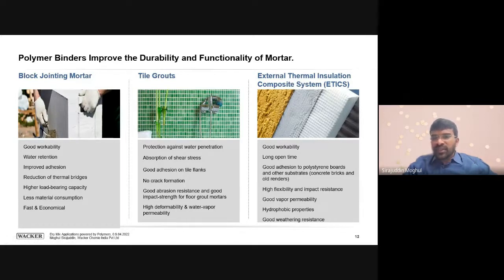It's an external thermal insulation composite system, where after constructing a wall, we use some polystyrene foam or some insulation material so that it insulates the building. And on that insulation material, we use mortar, and on that mortar we can apply paint, otherwise we can apply some texture plaster. So this is a composite system. In this composite system, the insulation material has to be adhered to the wall using a cement mortar, and that is not possible if it is not polymer modified.